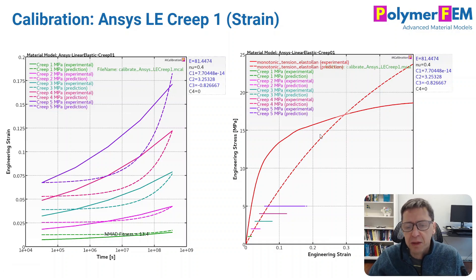The nature of this predicted strain versus time, the amount of creep strain, is not matching the data that well. And the monotonic test doesn't look so good either. The average error for all of this data at once is 16.2%. I'm not super thrilled with that.